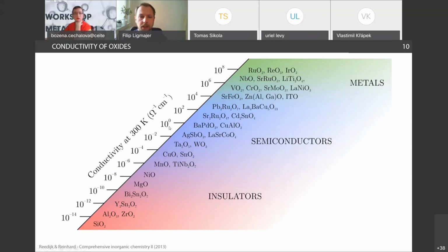VO2 is an oxide, and it still seems fascinating to me what is the range of conductivities various oxides can exhibit. So most of you know probably silicon dioxide, glass or silica, MgO, magnesium oxide, and others, which are fairly good insulators. They are transparent and very often used just because of this property. But there are other oxides which have conductivities quite similar to metals actually, and this range is really large. Yeah, this is something like more than 20 orders of magnitude, which is really impressive.